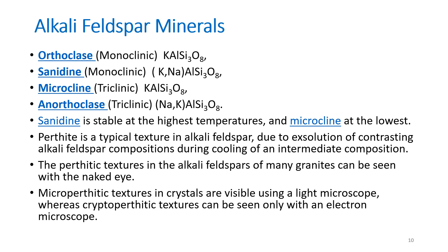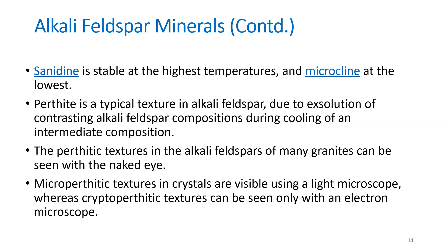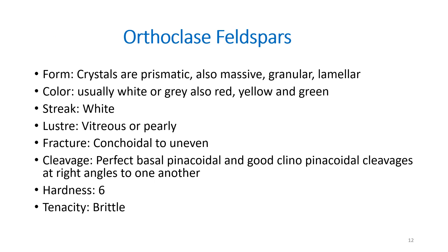Perthite texture is formed in alkali feldspars due to exsolution of contrasting alkali feldspars during the cooling of an intermediate composition. Perthitic textures in alkali feldspars of many granites can be seen with the naked eye; microperthitic textures in crystals are visible using a microscope; whereas cryptoperthitic texture can be seen only with an electron microscope.